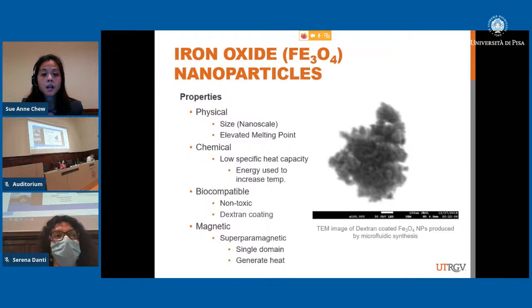These particles are able to generate heat when a magnetic field is applied to it. It's so far shown to be non-toxic, and we are also using these particles that are dextran coated. So the dextran prevents the particles from sticking together as they grow closer to one another, and when they stick, that can cause more toxic effects. So we make sure that we're using the dextran coated one.